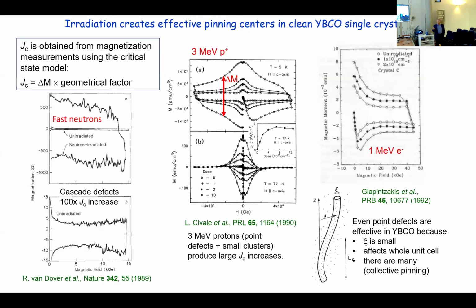So you have to be careful how you map. You have to know what the DPA is in one case or the other. The type of defects is different, but in both cases, what you have is randomly distributed localized defects. In this case they are mostly cascade defects. In this case they are small clusters, and they are very effective. Even electron irradiation, which only produces Frenkel pairs, point defects, is effective. Less effective, but somewhat effective. And that is because the coherence length in YBCO is so small that even point defects can act as pinning centers.